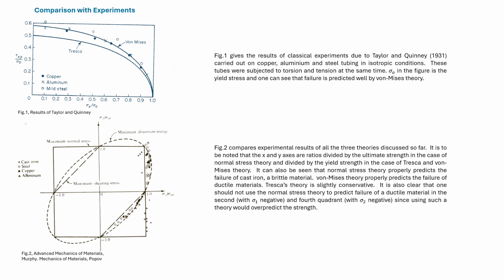Here we compare experimental results with the theories. This helps us understand the validity of the theories. These are the classical results of Taylor and Quinney. They carried out experiments on tubings in isotropic conditions. The tubings were subjected to tensile stress and torsion. Due to tensile stress, it was subjected to normal stress, and due to torsion, it was subjected to tau. Sigma 0 here is the yield stress. The materials considered were copper, aluminum, and mild steel.